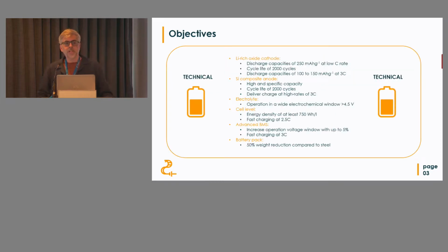Regarding the objectives, we have very specific objectives, which are also very challenging. Regarding the cathode, we are working with new and more exotic compositions, called lithium-rich oxides, which are composite oxides of rhombohedral and monoclinic phases. We are expecting to reach discharge capacities beyond 250 milliampere hour per gram at low C rates, together with a long cycling of 2,000 cycles. And we are looking for fast charging up to 3C, delivering between 100 and 150 milliampere hour per gram.